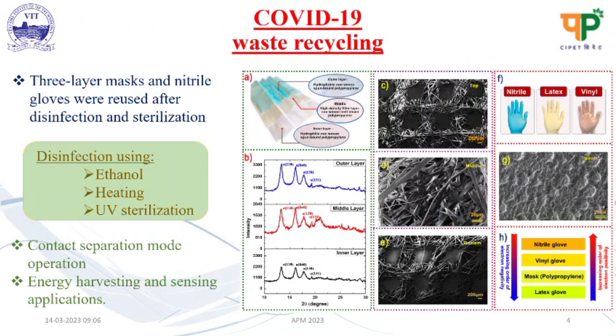The inner and outer layers are made of non-woven spun-bond polypropylene and the middle layer with melt-blown polypropylene. The XRD analysis of these three layers were examined in the 2 theta range of 10 to 30 degree, and it was noticed that the characteristic diffraction peaks alpha 110, 040, 130, and 131 are similar to the XRD of neat polypropylene. Here the figures C, D, and E are the scanning electron microscopic images of the surface of the mask layers.